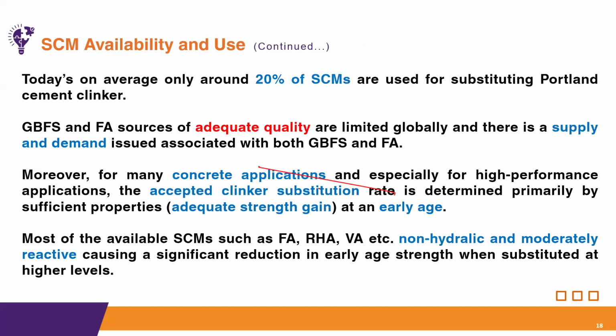So actually today, on average, only around 20% of SCMs are used as a substitute to Portland cement in the concrete. And there is actually a problem associated with the most popular slag and fly ash, which is that the availability of adequate quality fly ash and GGBS is now limited. There is also a supply and demand issue because of the global shift from coal thermal plants to renewable energy resources, and also from ground granulated blast furnace slags to electric arc furnace slag. Because of this shift, there is an issue with the supply and demand of both fly ash and GGBS.